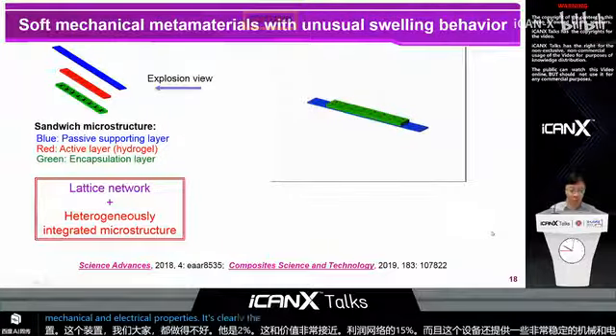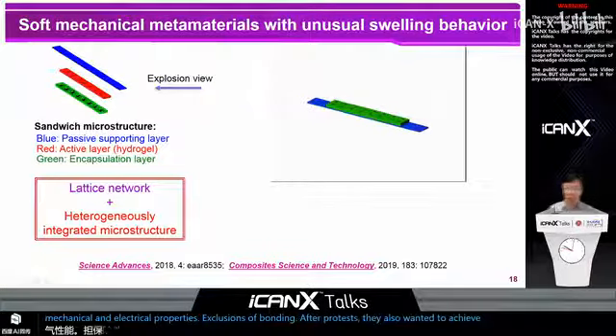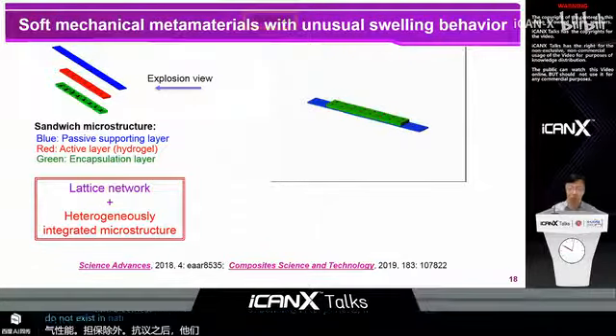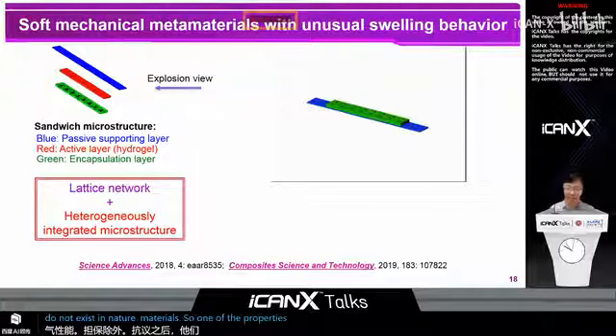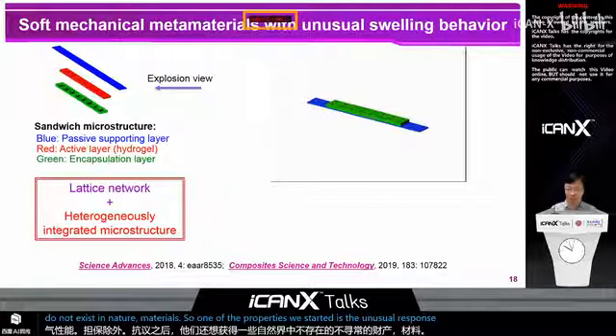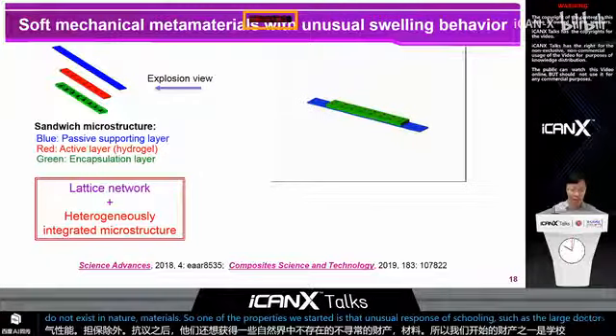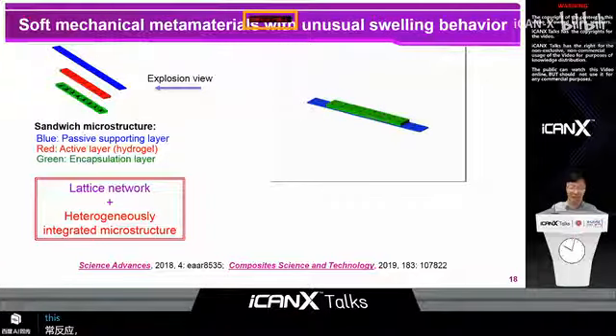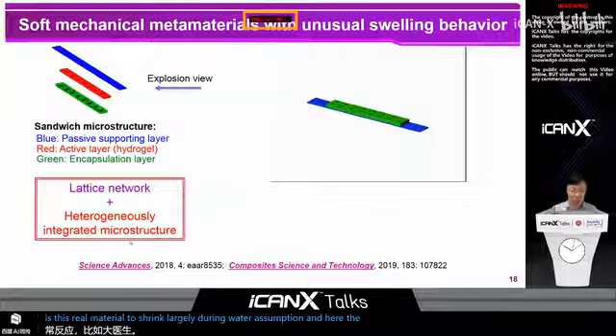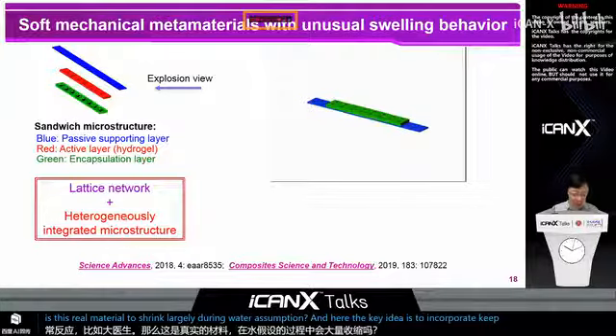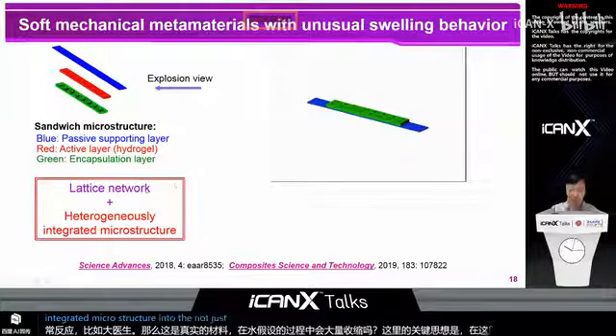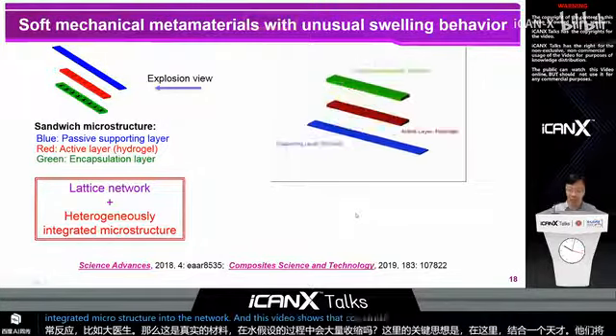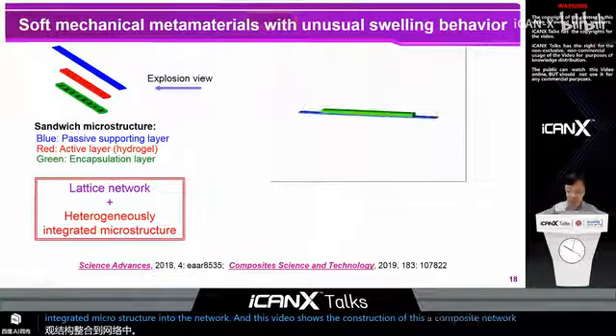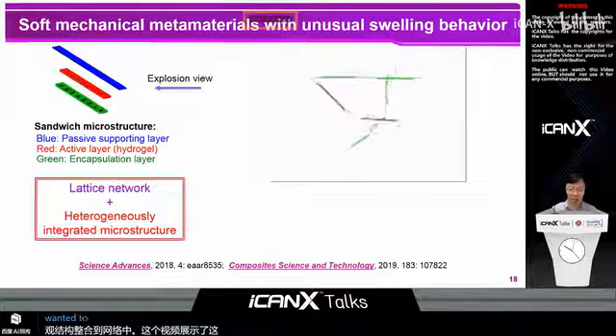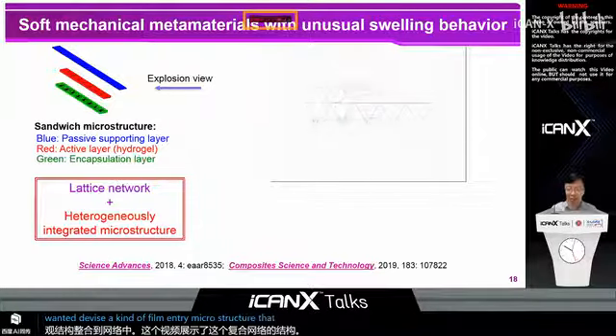Besides the biomimetic properties, we also want to achieve some unusual properties that do not exist in natural materials. One of the properties we studied is the unusual response of swelling, such as a large negative swelling. This requires the material to shrink largely during water absorption. Here the key idea is to incorporate heterogeneously integrated microstructures into the lattice network. This video shows the construction of this composite network. In short, we want to devise a kind of filamentary microstructure that shrinks largely during water absorption.